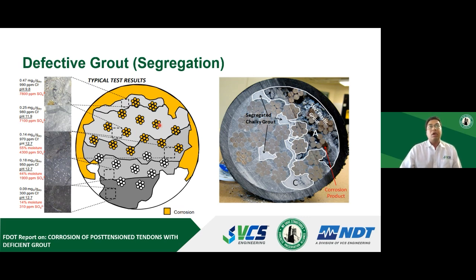It can be clay-like, or when the water has completely dried out, it can be powdery material, and that provides essentially no strength or no bonding. Whereas at the bottom, you have really good bonding to the grout. This chemical incompatibility and strength incompatibility can result in corrosion, where the top tendons can experience significant corrosion because of lower pH or lower alkaline environment, whereas the bottoms are completely immune to corrosion, especially because of the high pH grout surrounding them. So segregation and voiding defects are two key concerns when it comes to bonded post-tensioning structures.